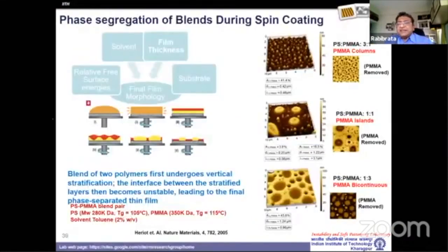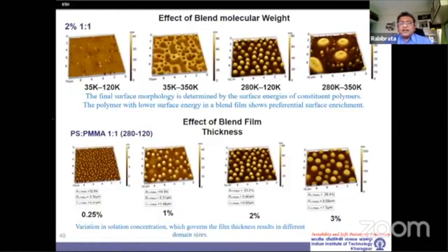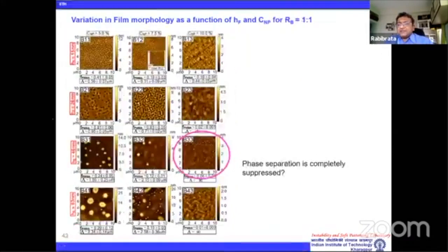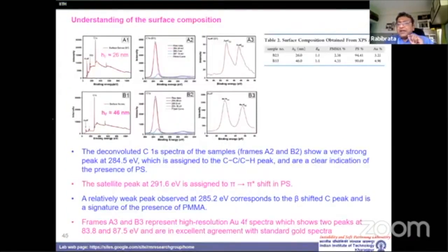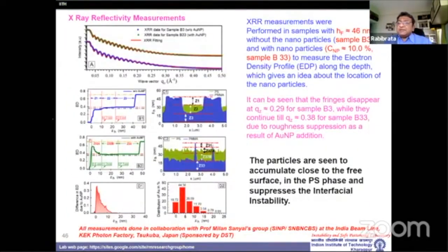because of the instability at the interface, because of the nanoparticle, that instability gets suppressed. And now what you are doing is, in a polymer blend, by adding some nanoparticles, you are almost getting, in a one-shot process, a bilayer, which otherwise you would have required two sequential spin coating steps. And if it can be scaled to dip coating or something like that, it can be an absolutely fascinating technique for creating multi-layer coatings in one go.